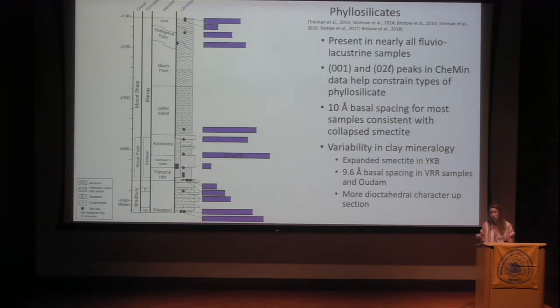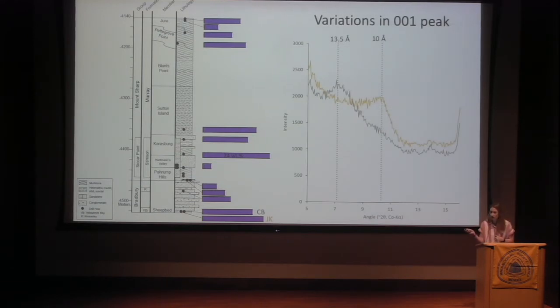But we do see some variability within the section, and the first thing I'll talk about is there is one expanded smectite at the base of the section in Yellowknife Bay. So these are the CheMin XRD patterns of those 001 peaks for the John Klein sample in yellow and the Cumberland sample in gray. These were both drilled from the base of the section just a few meters apart laterally, but the phyllosilicate in John Klein has a 10 angstrom basal spacing, but the phyllosilicate in Cumberland has a 13.5 angstrom basal spacing. So remember, Yellowknife Bay had that evidence for magnesium-rich fluids moving through here. So our hypothesis is that those magnesium-rich fluids partially chloritized the smectite here, so precipitated some magnesium hydroxide in the interlayer site to keep that structure propped open.